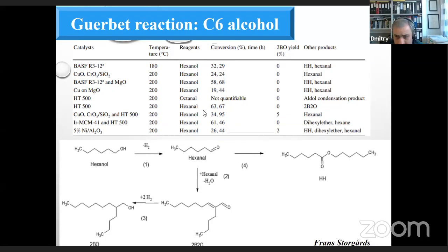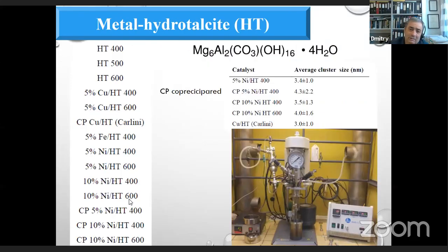And as you can see here, sometimes the conversion was, for instance, 34%, while the reaction time was 95 hours, and we got only hexanal. So once again, our target compound was this one. And even with the best catalyst, which was hydrotalcite, we were not able to get the target compound.